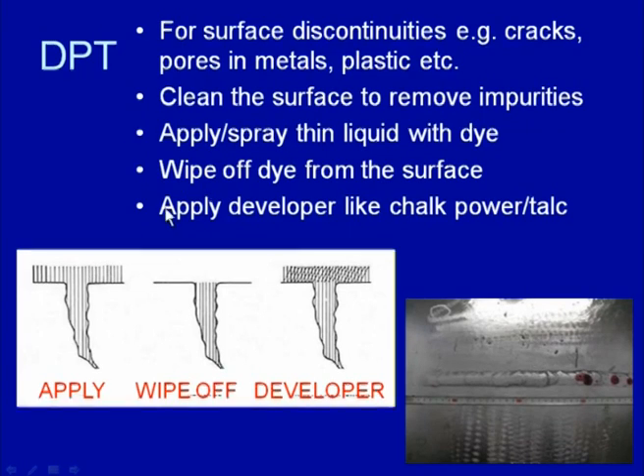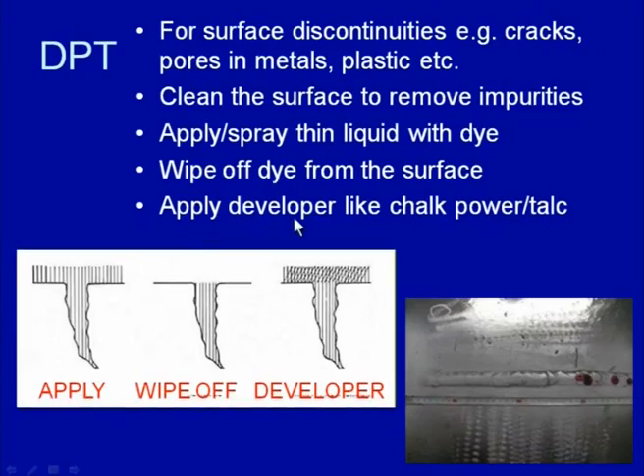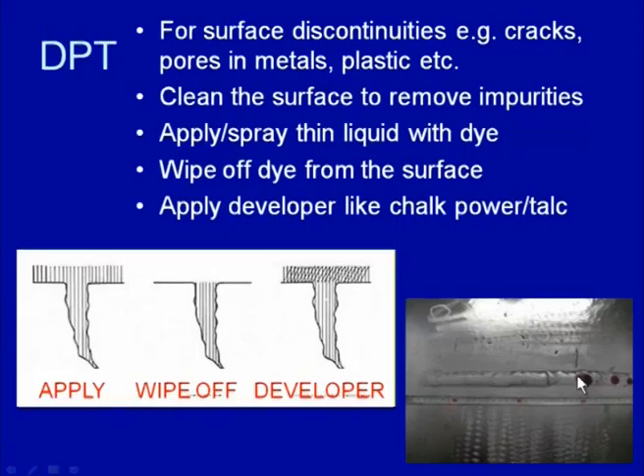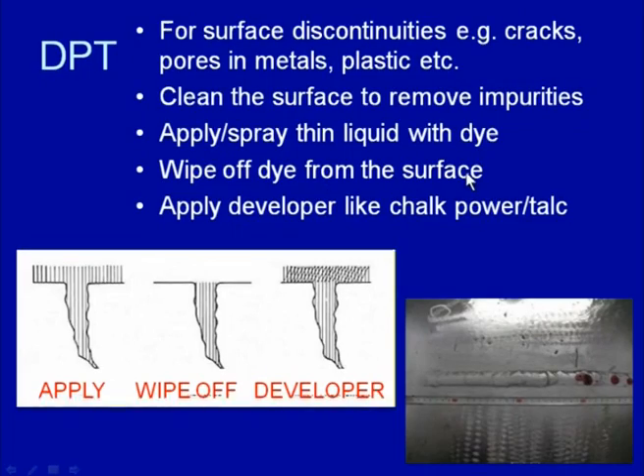When this thin liquid is applied, it is sucked by capillary action inside the defects present at the surface. After wiping it off, the developer, like chalk powder or talc, is applied, so that the developer sucks the liquid from those fine discontinuities present at the surface, and it develops some sort of stain, say red stains in the weld joint, indicating the presence of discontinuities at the surface. And if no defect is present, then on removal of the liquid, the whole of the liquid will be removed, and on the application of the developer, no stains will develop.